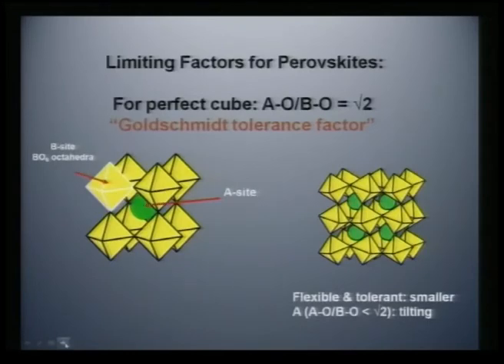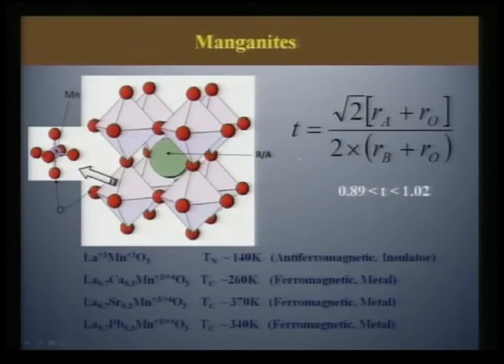As you know, in the previous slides, in the other modules, I have discussed with you the perovskite structure, and what is important for the perovskite structure is the tolerance factor, which was proposed by Goldschmidt, and this tolerance factor is very critical. If you have the optimum average A site size, then you would get a perfect octahedra. Okay, this is a cubic unit perovskite cell. But once you start substituting bigger ions or smaller ions in the lanthanum site, they can get distorted, and therefore there is a critical tolerance limit to which we are bound, and that is actually given by this tolerance factor, which has to be not less than 0.89 and should not be more than 1.02.